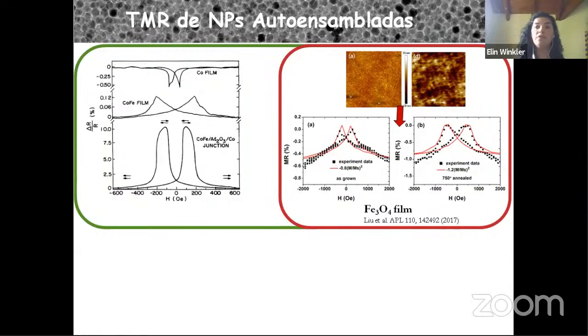So there are also simpler systems where the tunnel magnetoresistance conduction is also observed. These, for example, are the granular films. Granular films are composed of half-metallic material, where the conduction depends on the orientation of the electrons, and in this case, the tunnel barrier is composed of the intergrain between the half-metallic material. So what is also observed again is that the system presents two resistance states. The resistance is lower when you measure, this is the resistance as a function of the magnetic field.